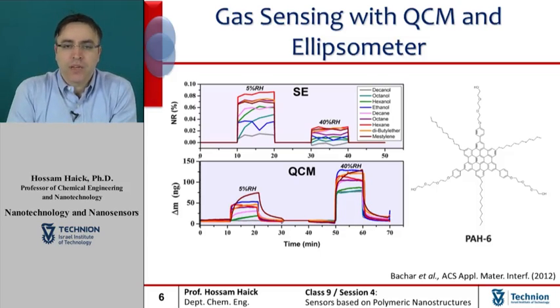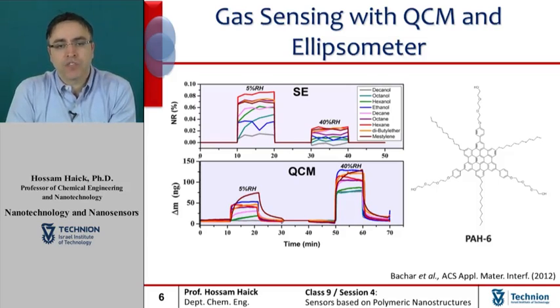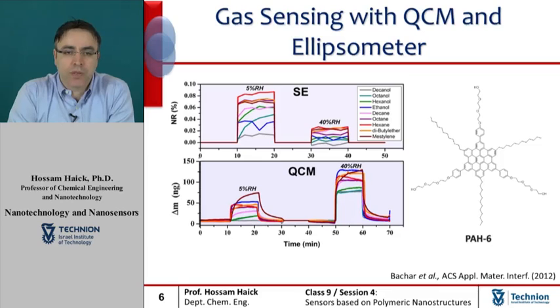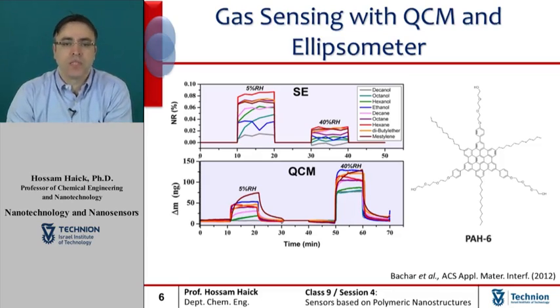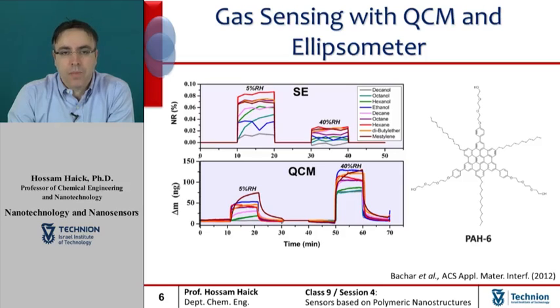Panel A of the presented figure shows thickness changes of the PAH film measured by spectroscopic ellipsometry upon exposure to various polar and nonpolar analytes in the presence of different humidity contents. Panel B on the screen shows changes in the frequency of a quartz crystal microbalance that is disrupted by the addition or removal of a small mass. Of course, this is done for a wide variety of concentrations of polar and nonpolar analytes in the presence also of different humidity contents.